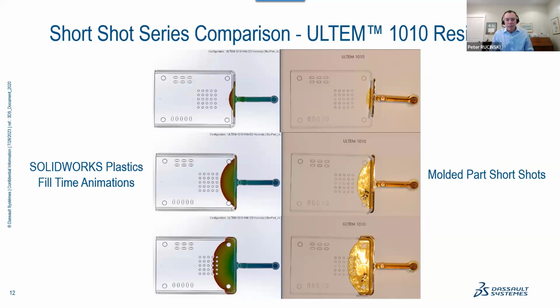Now, if you're not familiar with short shot series, this can be somewhat of an inexact science because let's say as we're looking at these short shots here, maybe the first short shot at the top is, I don't know, not even 5% filled, and maybe the second one is 5 to 10% filled, and the third one is 10 to 15 or 18% filled, or something like that. Well, when you're actually molding these parts in these short shots, it's not possible to just stop the machine at 10% filled. And the other thing that you have to think about is that as this melted material flows into the mold cavity, it's under compression, and when you release the pressure on the system, the material can actually continue to flow as it decompresses a little bit. So that's all to say that it's not exactly easy.